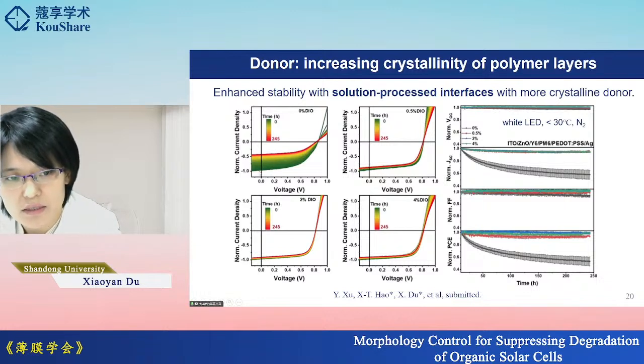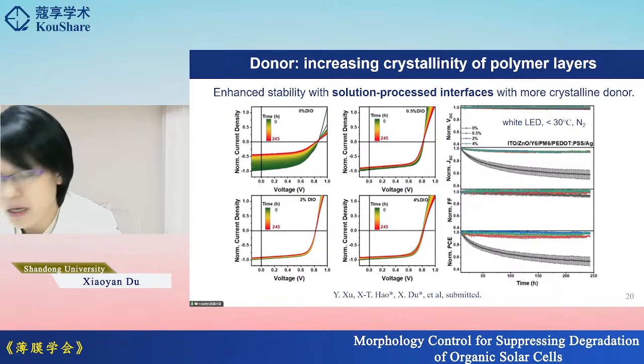So this degradation is attributed to the interaction of PEDOT:PSS material with the amorphous PM6. With this result, I think we can see that if we increase the crystallinity of the polymer layers, we can somehow lock the diffusion of the non-fullerene acceptors, and also we can make the interfaces very stable.